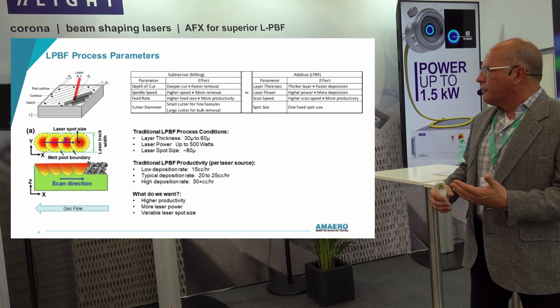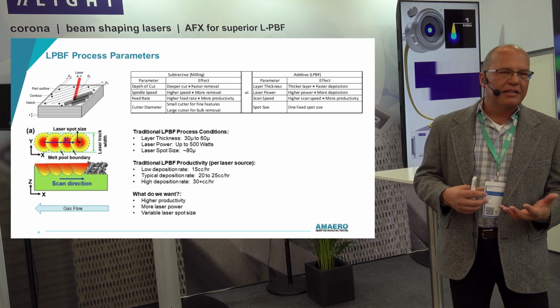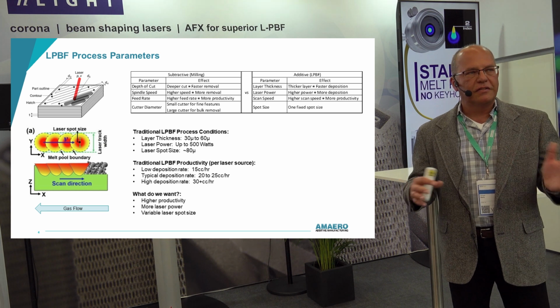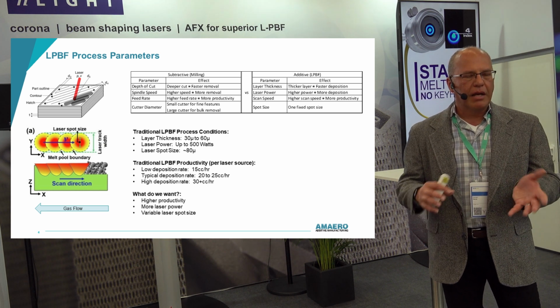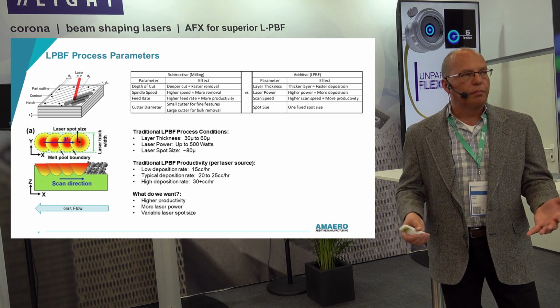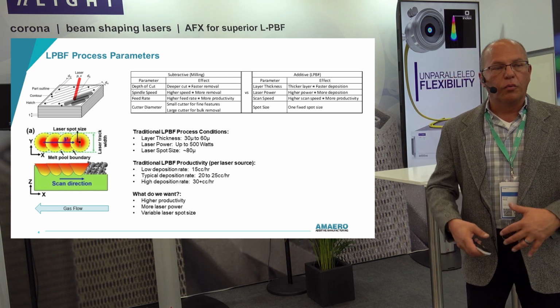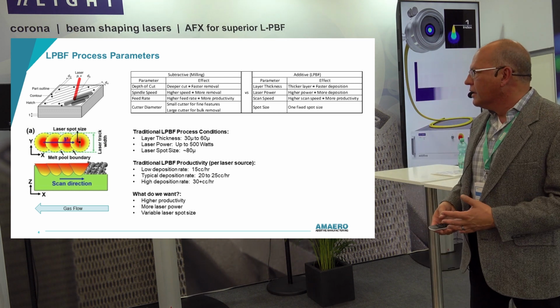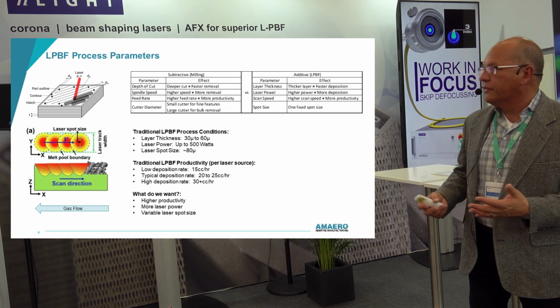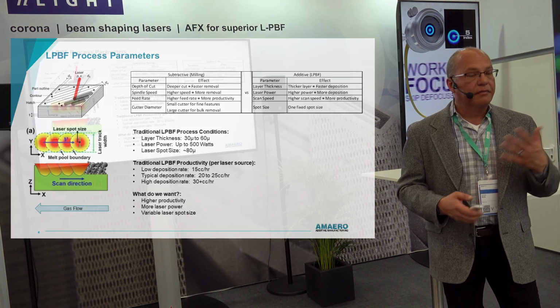From a productivity standpoint, we deposit between about 15 and 30 cc's per hour, nominally around 20. We'd like to be more productive, and that's always our goal, why we want to put more laser power in. So what do we want? We want higher productivity, more laser power, and a variable spot size.